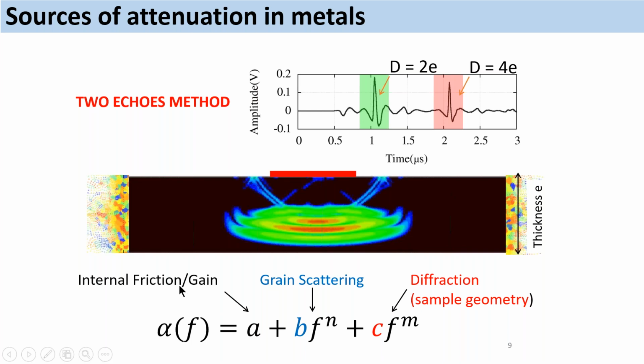And it's often due to the presence of little defects in the sample, such as dislocations or the moving of carbon atoms between lattices, and this contribution is usually small. The main contribution that we are very interested in is the grain scattering contribution. We will come back to this contribution, but this scattering occurs because the grains are oriented in different directions and the wave will be scattered in various directions due to those grains present in the sample.